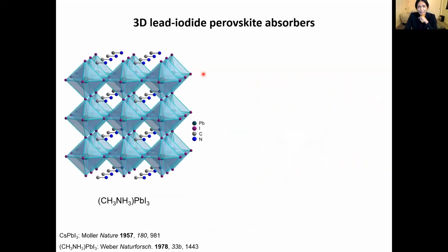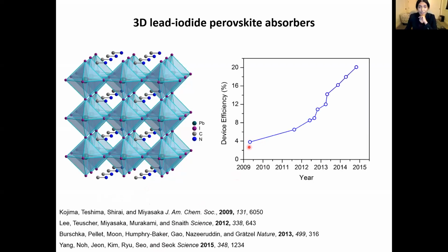So the material that has really caught the photovoltaic industry by storm is shown here. This is the perovskite that I initially introduced. There's lead in the center and iodides surrounding the lead. These lead iodide octahedra share corners to occupy 3-dimensional space. And in these voids, we find methylammonium as the A-site cation. This material is not new. It's been known for decades. But in 2009, Miyasaka's group decided to evaluate this material as a photosensitizer in a solar cell, and they got a really decent device efficiency of 4%.